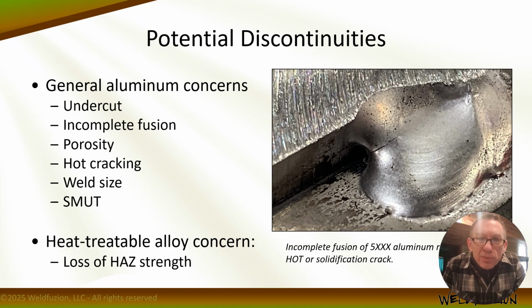Aluminum welding challenges, potential discontinuities include all the common issues we see with pretty much every material, right? Undercut, incomplete fusion, porosity, cracking, and insufficient weld size. But the cause and conditions differ slightly from steel alloys, and you might also see some soot material on the welds. Heat treatable alloys undergo a significant loss of strength in the heat affected zone, and thus thermal management remains an issue, right? So we have to control our heat input so as not to completely reverse the effects of heat treat conditions.